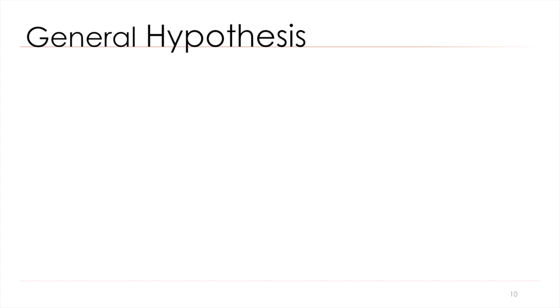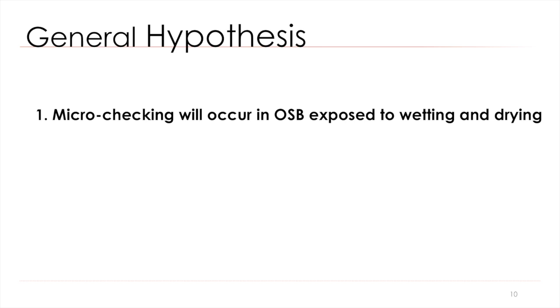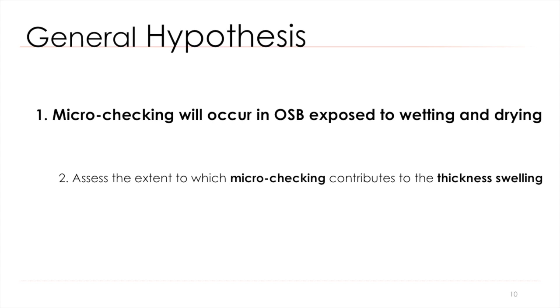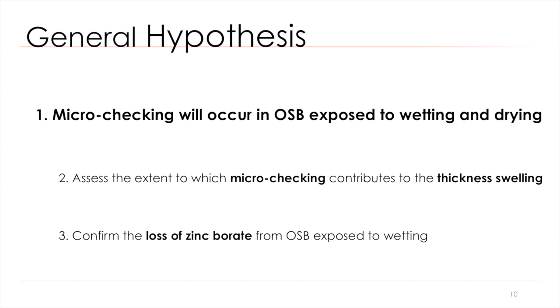So that leads us to our hypothesis, where we want to test if microchecking will occur in OSB exposed to wetting and drying. We also want to assess the extent to which microchecking contributes to the thickness swelling of OSB, and confirm the loss of zinc borate in OSB exposed to wetting.